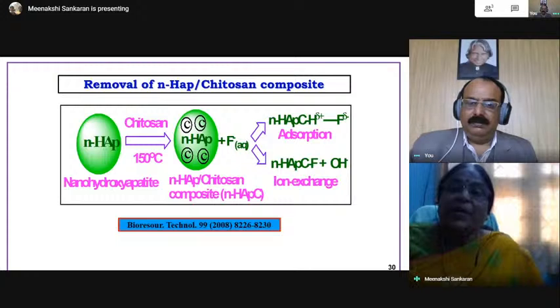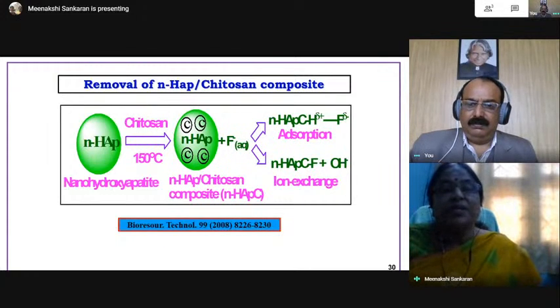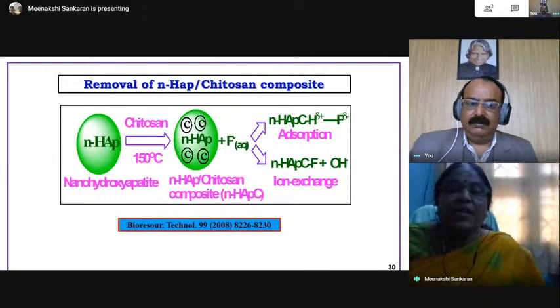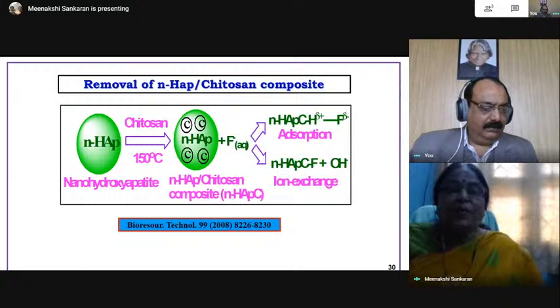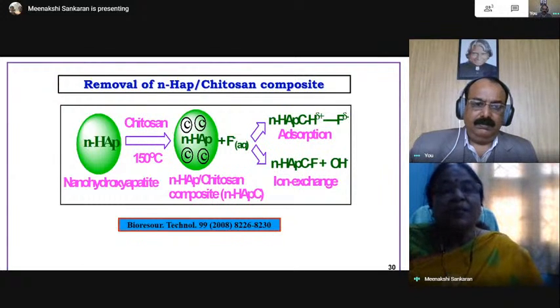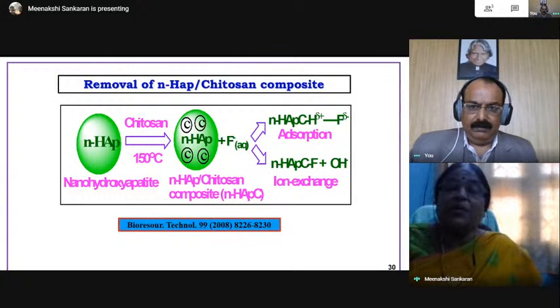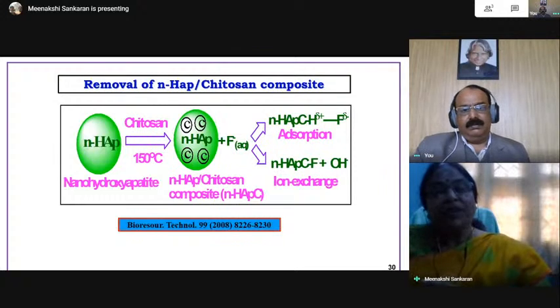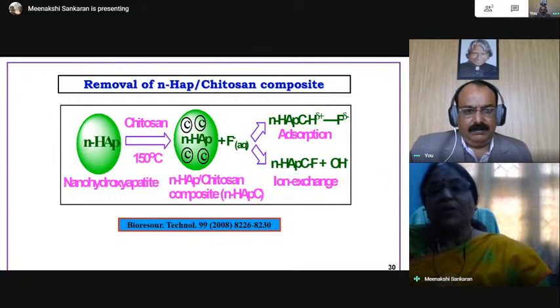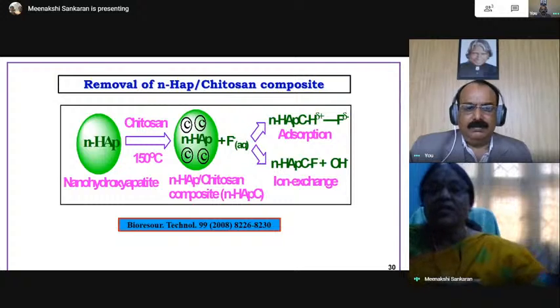And nanohydroxyapatite chitosan composite. Nanohydroxyapatite is also a very good inorganic material which is capable of removing fluoride. It is also in the form of powder. As such, it cannot be used for technology transfer because the powder form will affect the filtration ability of the material, and it is rigid. Therefore, we have mixed it with chitosan. Chitosan, because of the amino group and hydroxyl group, is capable of removing fluoride. When we mix them, the synergistic effect works, and both are capable of removing more fluoride. Here also the mechanisms followed are adsorption as well as ion exchange.